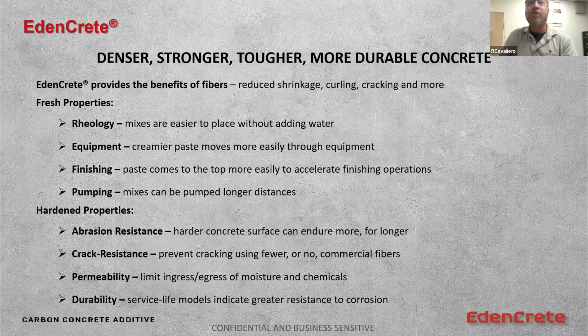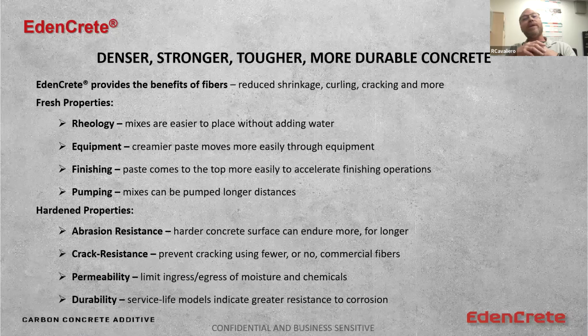So the benefits that EdenCrete provides, the mechanical aspect of the carbon nanotubes, right? We help to bridge cracks. We help to reduce shrinkage. We help to reduce curling, and we help to reduce the cracking that's associated with the concrete's response to that. So even for an identical level of shrinkage strain, we'll see that the concrete without EdenCrete might crack and the concrete with EdenCrete will not for a longer period of time, right?